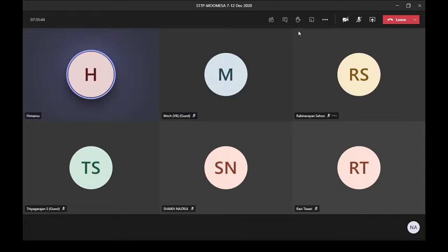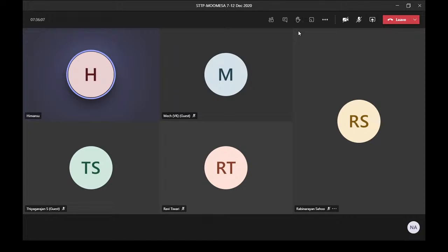So, as a summary of this part, we discussed several platforms. In the initial part I talked about biomaterials, and now I talked about bioadhesives. These are the two common bioadhesives I have discussed. One is PAMAM, that is polyamidoamine derived or dendrimer based. Another is polycaprolactone based. Polycaprolactone is usually solid. We prepared a liquid formulation, polycaprolactone triol, which could be attached with a bromodiazirine group, and we can get strong adhesives.